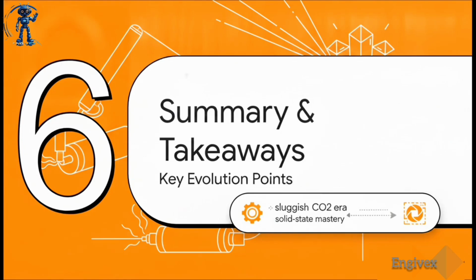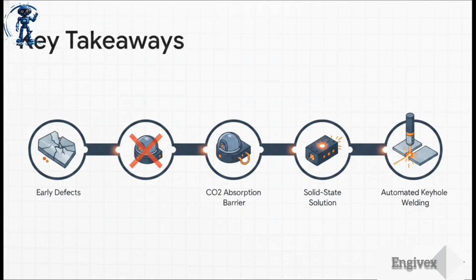All right, wrapping things up with Section 6, Summary and Key Takeaways. Let's quickly recap the main things you need to take away from today. We started with the basic problem. Aluminum's crazy high reflectivity and rapid thermal conductivity originally caused extreme weld defects. Early CO2 lasers running at 10.6 microns simply lacked the necessary absorption to efficiently couple with the aluminum at all. The massive game-changing shift happened with solid-state mediums, like fiber and diode lasers, operating at around 1.06 microns. That shift solved the fundamental absorption barrier completely. And today, that high power density gives us stable keyhole welding at speeds over 10 meters per minute, allowing remote, dual beam, and deposit welding techniques to absolutely dominate modern automated assembly.